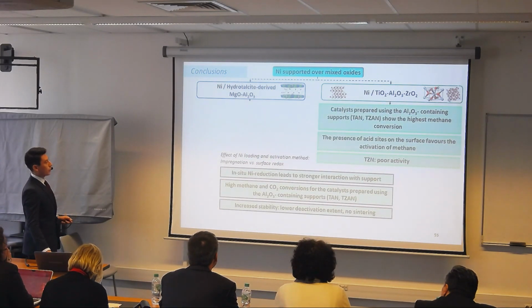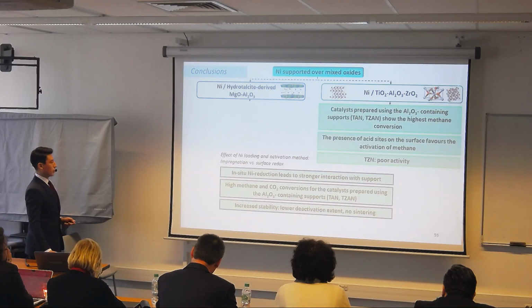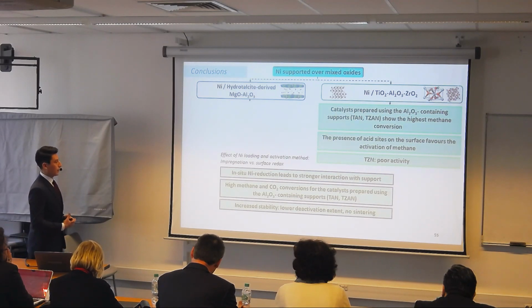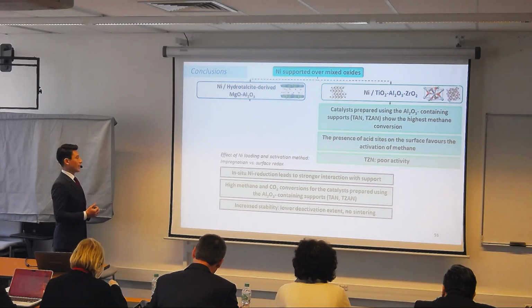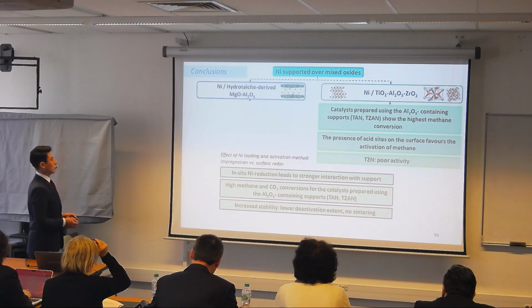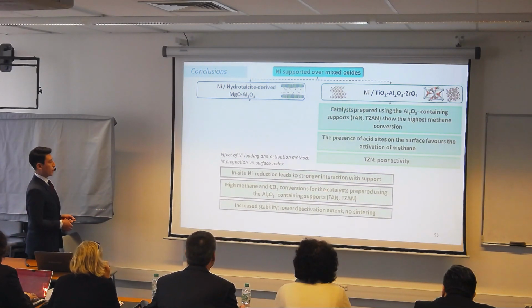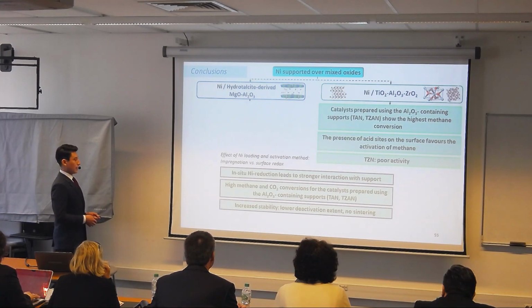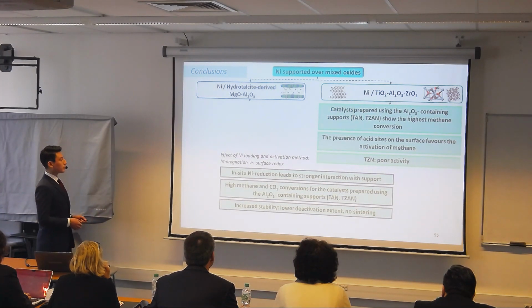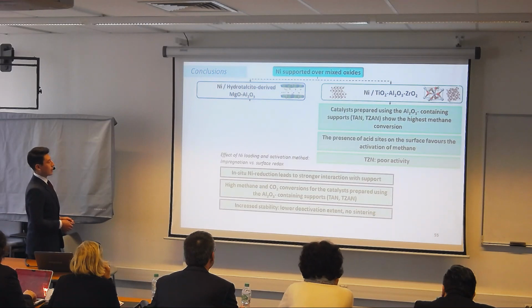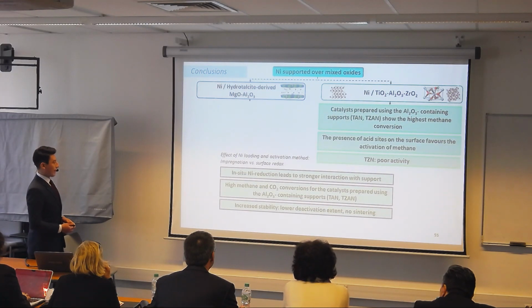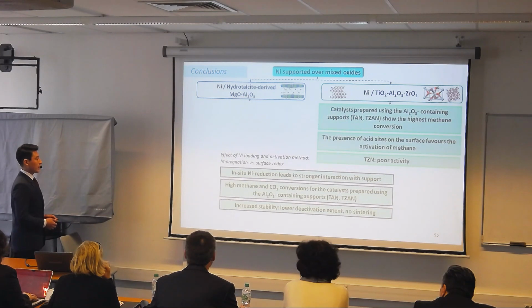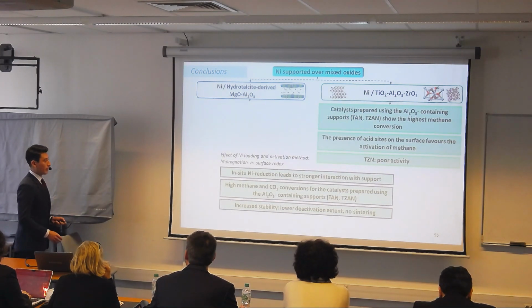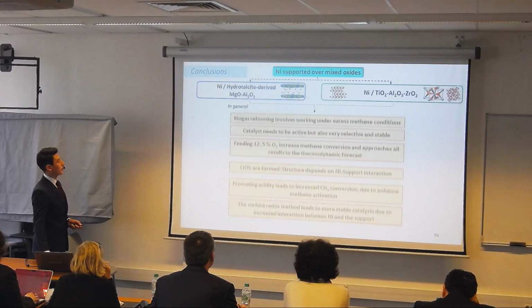In the last part, we saw a new method of introducing nickel. We see that in situ nickel reduction leads to a stronger nickel-support interaction that leads to high methane and CO2 conversion for the catalysts prepared by this method, mainly for the ones containing alumina. This method allows increased stability. We have lower deactivation, and we didn't find sintering.